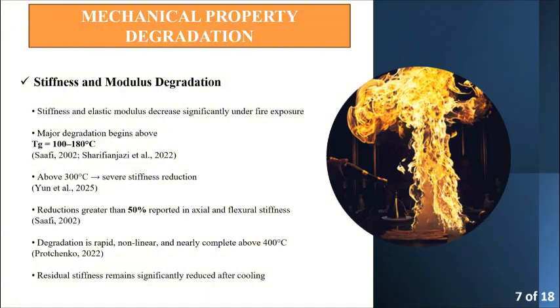If the temperature is above 300 degrees Celsius, the reduction becomes much more serious. Research shows that stiffness can decrease by more than 50%, as Saafi have already mentioned in their studies. At temperatures above 400 degrees Celsius, stiffness can completely collapse, which is very dangerous. It is also important to understand that this reduction happens quickly after exceeding Tg, which we mentioned in the introduction, and it is not fully recovered after cooling.